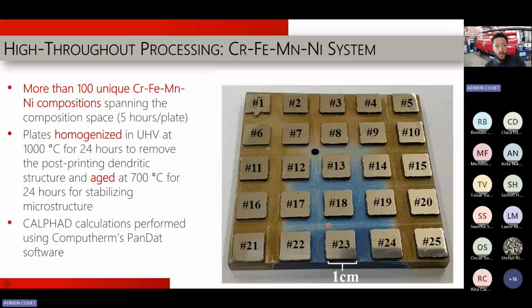You see some micro porosity. It's there, right? It's difficult to avoid, but it's below about 0.1%. We've quantified it, so it's really minimal, and it's not at a level that will actually impact your corrosion test significantly in molten salts. So we're not really worried about this.